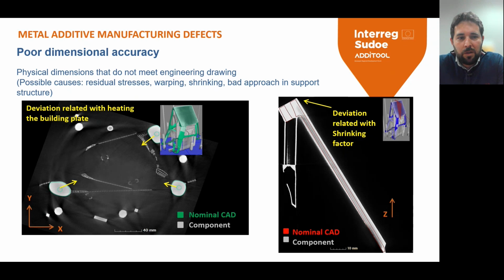So talking about dimensional accuracy, poor dimensional accuracy could be obtained by different causes, such as residual stress, shrinking, bad approach in support structure, etc. In the image on the right, which is a CT, a computer tomography cross-section again, you can observe the deviation related with the shrinking of the part. And what does it mean? The manufactured layer height is not exactly the same height of the nominal value. So for a large component, this deviation is cumulated, obtaining, for example, between 0.5 to 1 millimeters deviation in the height of the component.